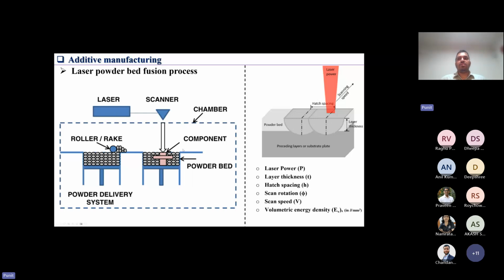There are several process parameters that are important in this additive manufacturing process. For example, laser power: how much power you are giving to the material during the process decides how much material you are melting in each line. The other processing parameters would be layer thickness, so what is the thickness by which you are spreading the powder and melting the material in each layer? And then hatch spacing: what is the spacing between two subsequent lines of these laser scans?